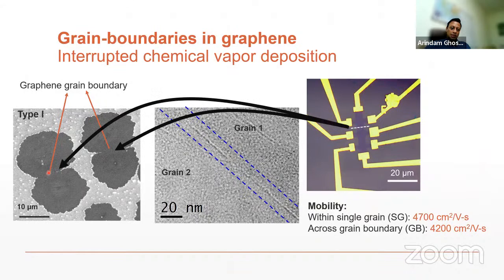And then you can measure the noise both across the grain boundary as well as in a region which doesn't have a grain boundary, and see if they're different. And from there, you infer whether there is any magnetic order or not. Okay, so this is called a grain boundary region. This is a single grain region.